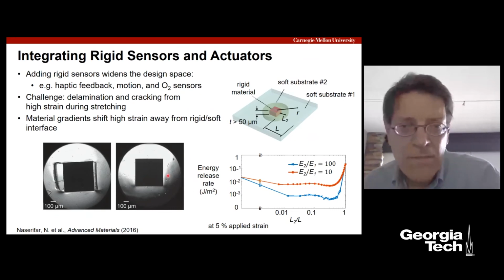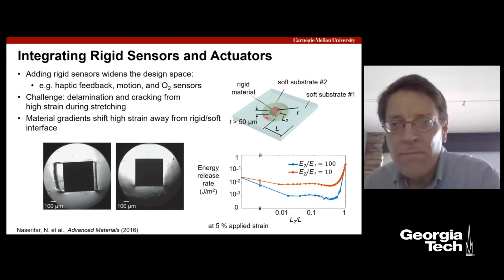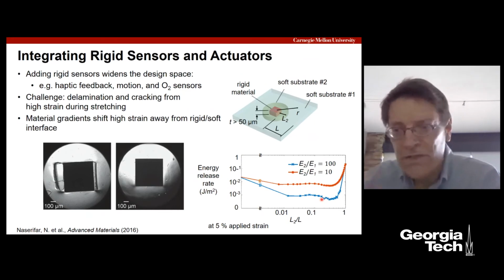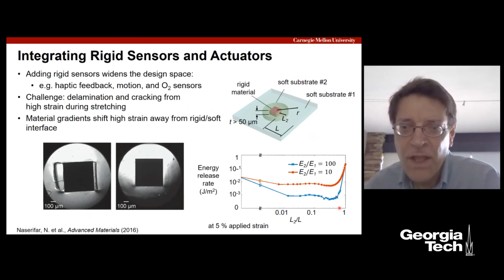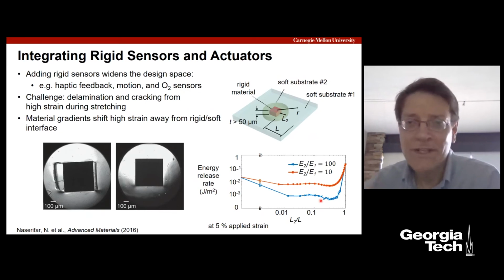So we started with making discs of 5:1 PDMS and embedding them in 20:1 PDMS, and looking at, okay, if we stretch these and have as a parameter how big the disk is, what happens? We do find that if we can make that Young's modulus difference large enough, and we can make a large enough disk, we can get a lower energy release rate for a given, in this case, 5% applied strain, but it would just go up linearly with that here. We'd be shifting the curve up and down. And so it's important to have a certain amount of a larger Young's modulus, as intuitively obvious, I guess, around a rigid chip for this to work.